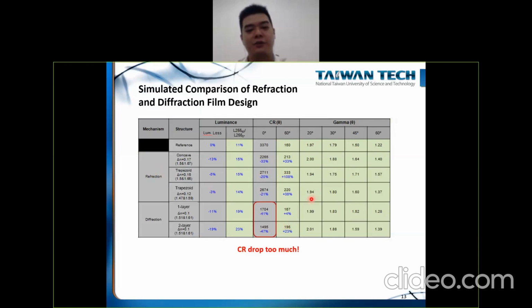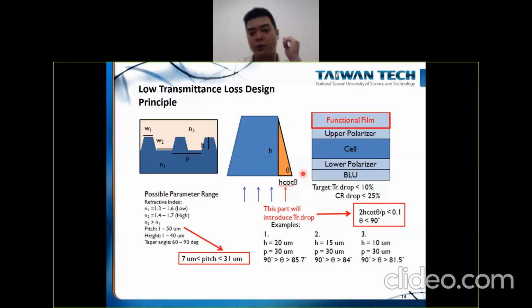And we go a step further, with a design target to maintain the transmittance drop below 10% and the contrast ratio drop below 25%. We try to analyze what will cause the transmittance to drop. For example, this part will induce the transmittance drop because light coming in this direction will be diffused to the large angle direction. So we can design based on the ratio of this part to the period of our structure, and we can control the transmittance drop.